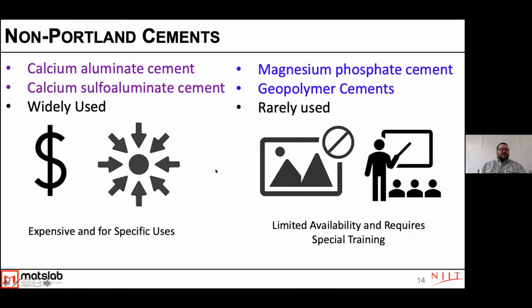So what's the difficulty with these? Well, those first two that are similar to Portland cement are already widely used, but we're talking about 5 to 10 times the cost of Portland cement. And they're really meant for very specific uses because they tend to set and harden very quickly. So they're a little bit more difficult to work with. Whereas with our Portland cement, we get a couple of hours. That gives us the time for the workers to bring it out to the field and place it. These ones we're talking about hardening in 10, 15 minutes. And so it gets really difficult to work with.